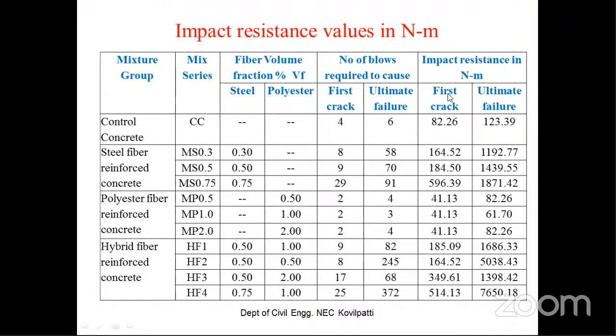First crack under impact load, this column shows the energy absorbed in the first crack, and the next column shows the ultimate failure. So for the control concrete, you just see it is only 82. For steel fiber reinforced concrete, the energy absorbed in joules ranges from 164 to 596. MS 0.75 volume fraction has reached 596 joules energy absorption capacity. And the polyester fibers have shown very poor resistance in case of impact. The energy absorbed is only 41.13, whereas the steel fibers have absorbed impact energy up to 596.